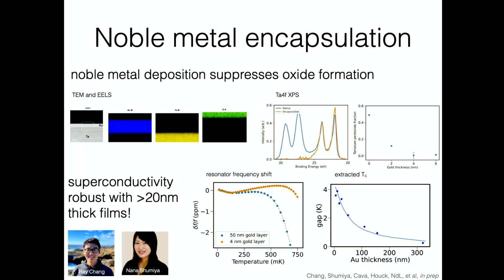Now, normally if I just spray a normal metal on top of my superconductor, that's a horrible idea because I've introduced a bunch of losses. But if I do a good enough job at making this hetero-interface, I can rely on something called the proximity effect, where Cooper pairs can just sort of exist in the normal metal, and the whole thing still acts like a superconductor.